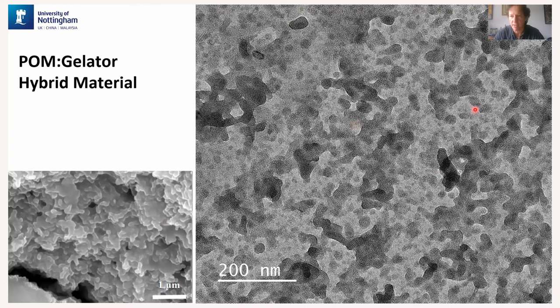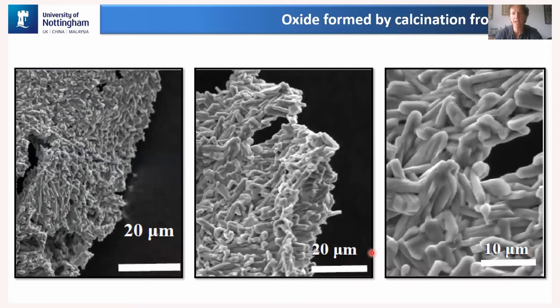So you can see these all over the place. So you can see it here as well, here as well, here as well. So it's not an artifact of luck. This is happening all through the sample where you're organizing that polyoxometalate. And you can actually use that to grow hybrid material. So if we now calcine that hybrid material, you get to the oxide form.